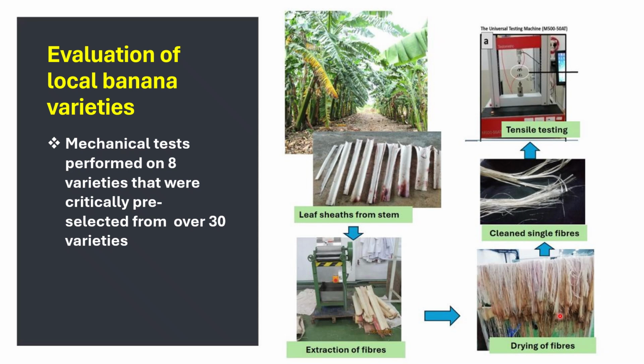The fibers were extracted, and the fibers were subjected to tensile testing. And now, having this mechanical data on the fibers is an important step in the fabrication of the mulch, because we just can't go blindly on fabricating mulch randomly on any fibers. So we characterize the fibers, and based on that, we selected one single variety for the fabrication of the mulch. And so to go ahead with that, we had to bear in mind what we are looking for in that mulch, and which variety would be best suited for us to make that agricultural mulch.